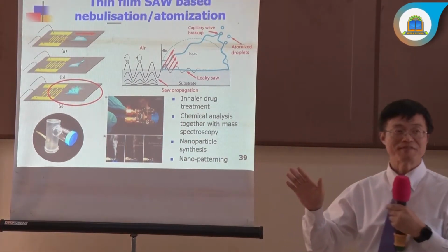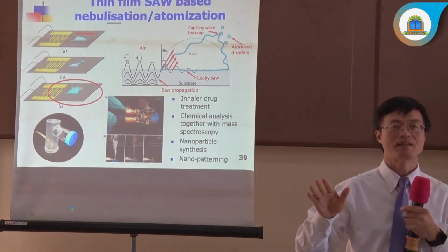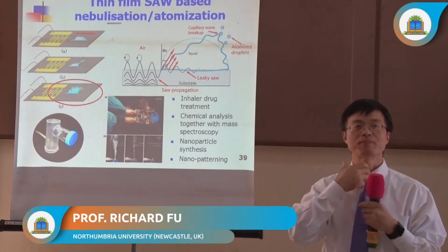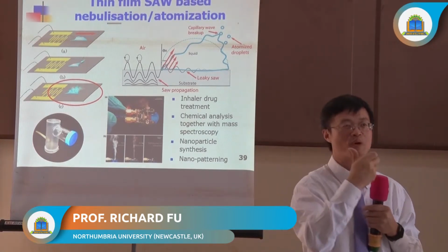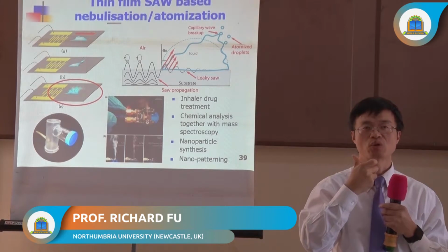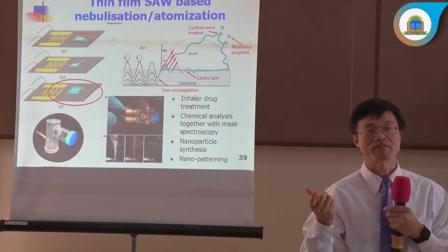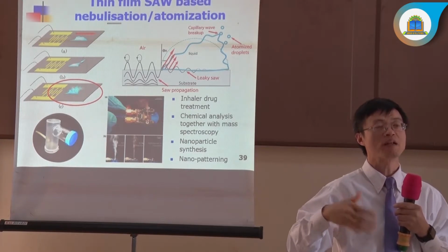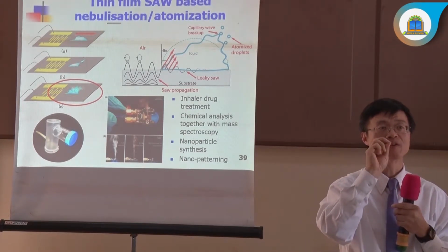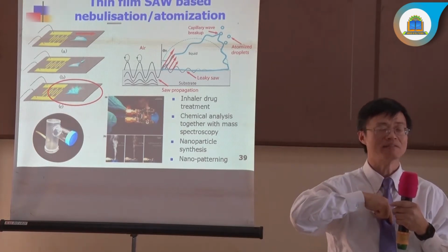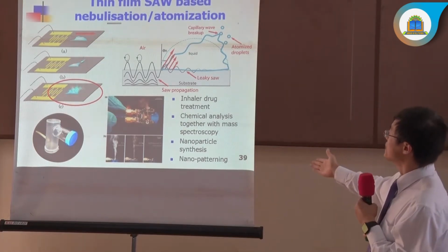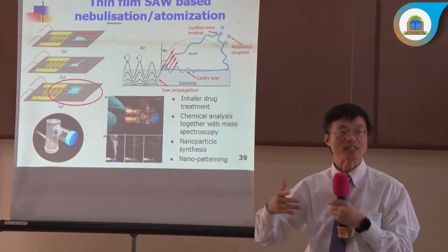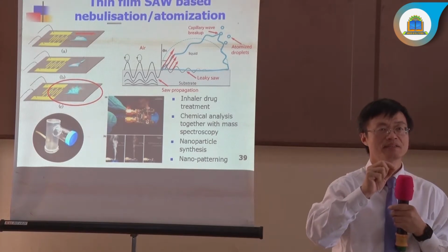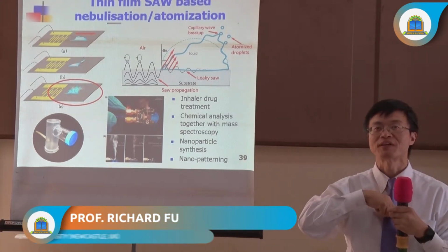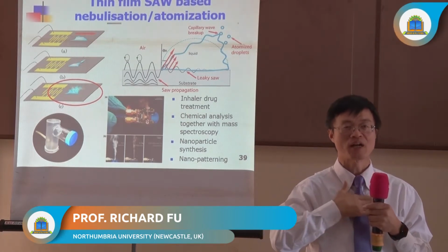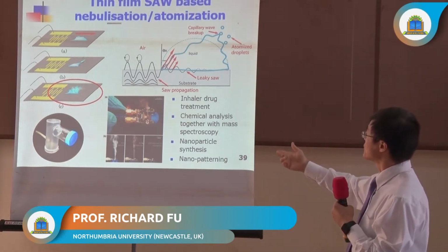Another very interesting phenomenon for surface acoustic wave is nebulization or atomization. If you have asthma, then you will buy some kind of mechanical drug inhaler. That's a mechanical wave. Normally, mechanical wave frequency is very low. Low frequency means the droplets generated are very, very large. They won't go inside your lungs efficiently. Surface acoustic wave has very high frequency. It will generate much, much finer droplets. The finer droplets will go much deeper into your lungs, which is more effective if you want to treat lung disease, right? So that is surface acoustic wave.